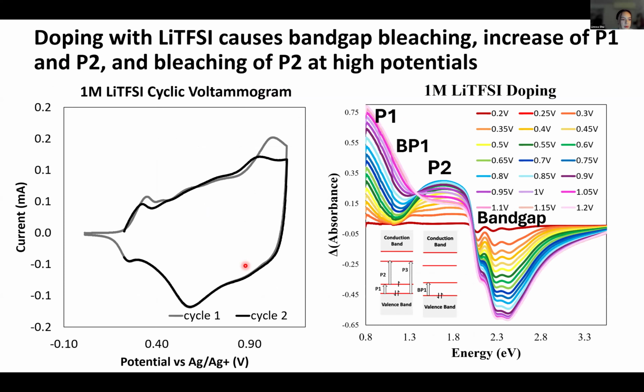So here's what happens when we dope. I pre-cycled the film twice and then doped on the 3rd cycle, which is what you see on the right. And I've plotted the change in absorbance from the pristine polymer film. So we can see that if we dope right here before the onset of the first peak, we get no change in absorbance between the pristine and the doped film.